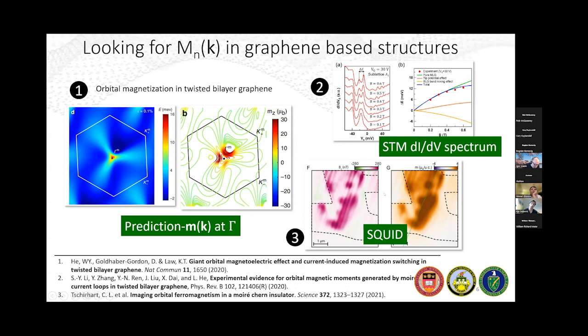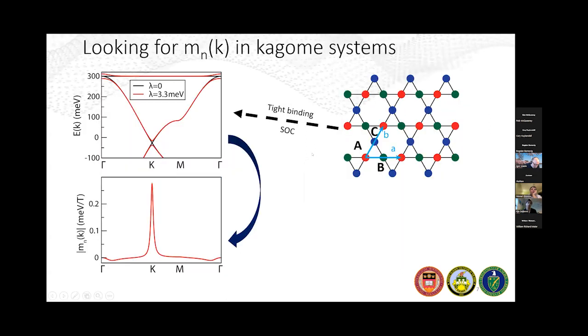And then probably a more direct evidence is something that you can get from net magnetization using SQUID. So this is from Andrea Young's group, where they were actually able to locally image this net magnetization in twisted bilayer graphene that otherwise has no spin magnetism. So this is just something that comes from orbital effects. So in our experiment, we set out to essentially investigate a similar kind of physics in the kagome systems.